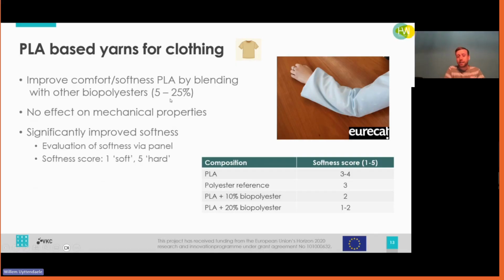So when we had these PLA clothings, we also tried to improve them further, improving the softness, especially of the material. We did this by blending them with other biopolyesters in 5 to 25%. What we saw is that by blending with 10 or 20% of another biopolyester, we could obtain these PLA blend fibers that are actually softer than a standard polyester reference that is woven and processed in the same way. So really quite a soft and comfortable material.